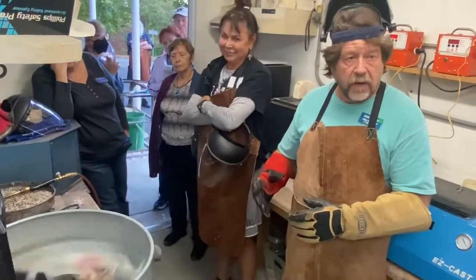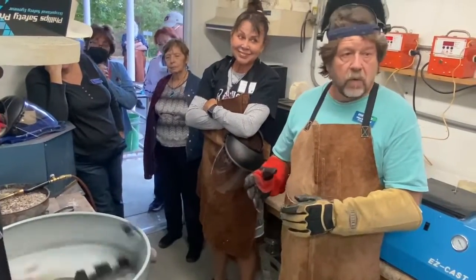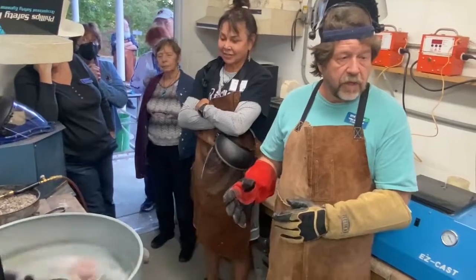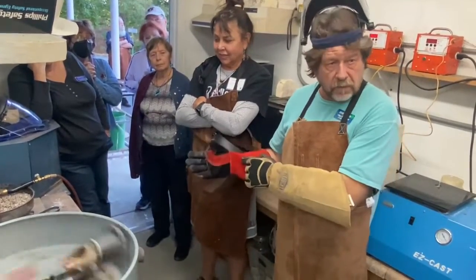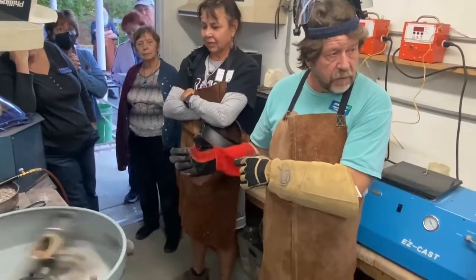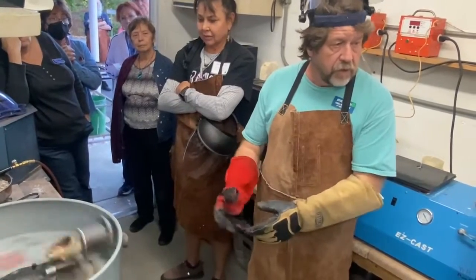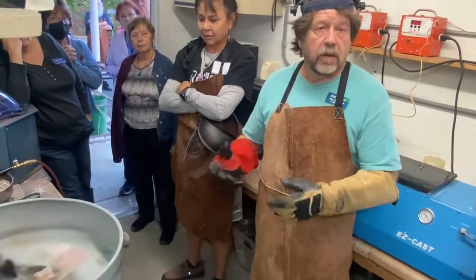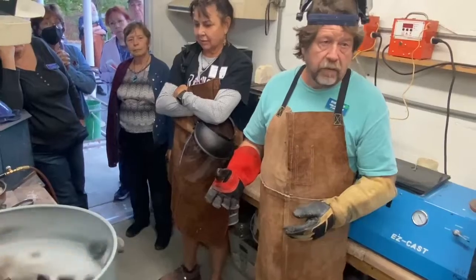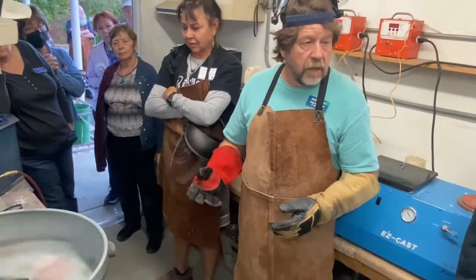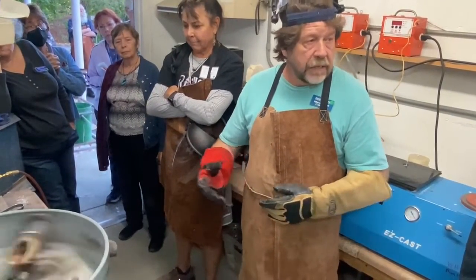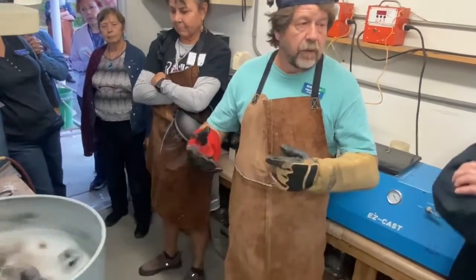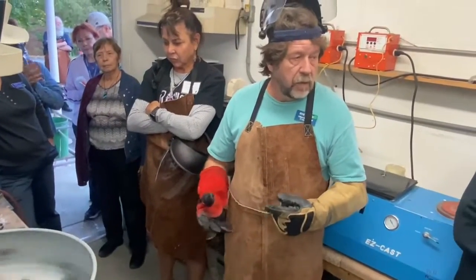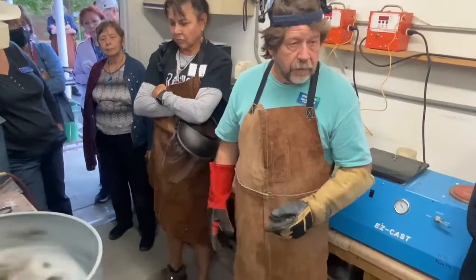It will also vary a lot with what metal you are casting. If you're casting argentium and you let it sit out there for 5 minutes and rest and quench it, it's going to shatter on you. You have to let it go at least 20 minutes. And there's a number of metals like that, newer metals. So when I say you need to know what your metal is that you're casting, if it's scrap, we need to know it because it'll either make or break the piece.